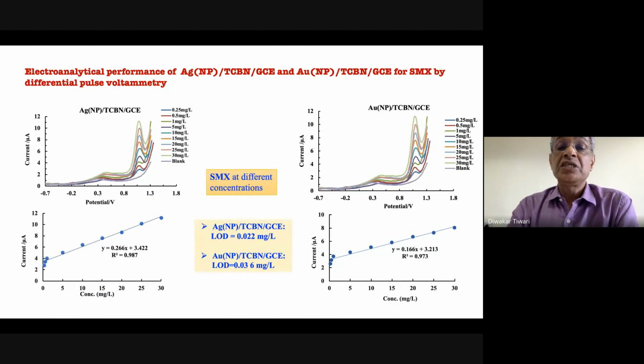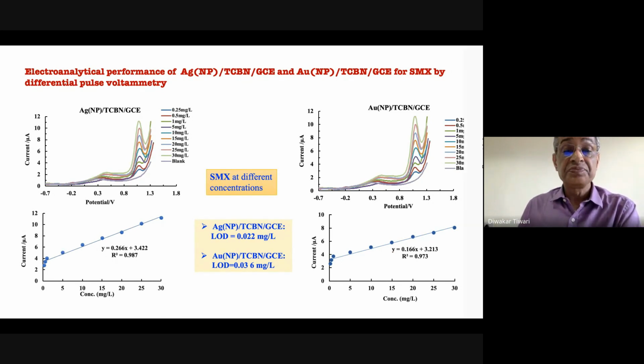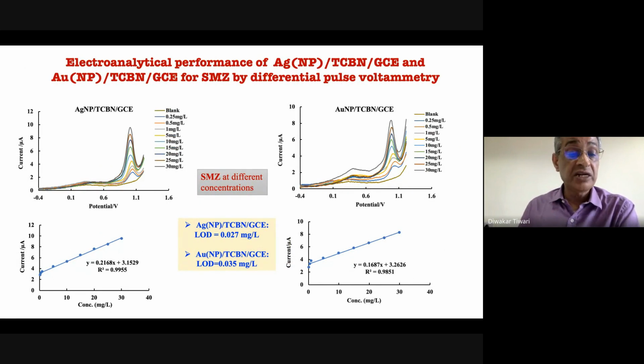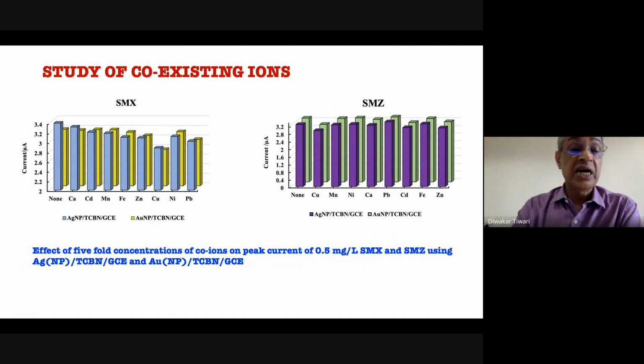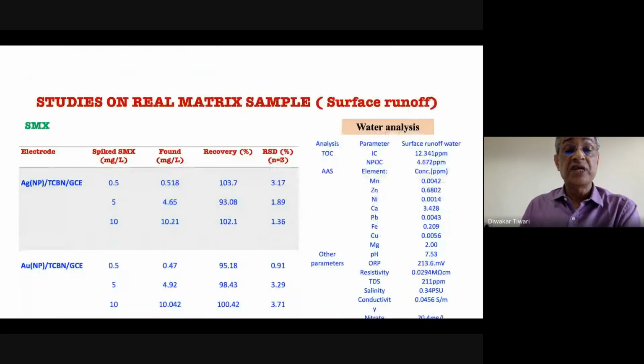And then using the silver and the gold based material, we tried to detect this sulfamethoxazole, and we have seen that with the help of this, a good calibration line is being obtained, and LOD was 0.022 milligram per liter, that is the ppm level, and for the gold based material we got 0.036 ppm. Similarly for the sulfamethazine we have done, and a good calibration line here also we could get, and with the silver and the gold based material the LOD, that is the limit of detection, is 0.027 and 0.035 ppm. These are the coexisting ions. Some of the ions, particularly like the copper and all, have hampered the detection, otherwise not significantly hampered.